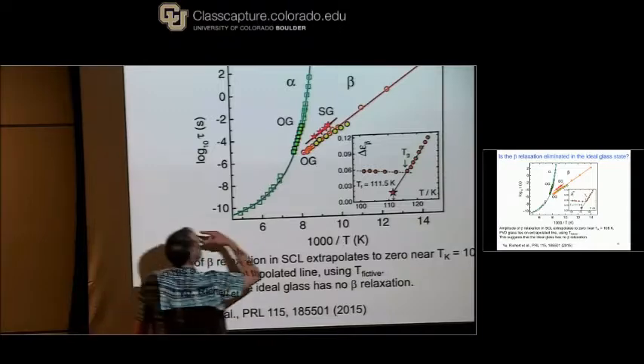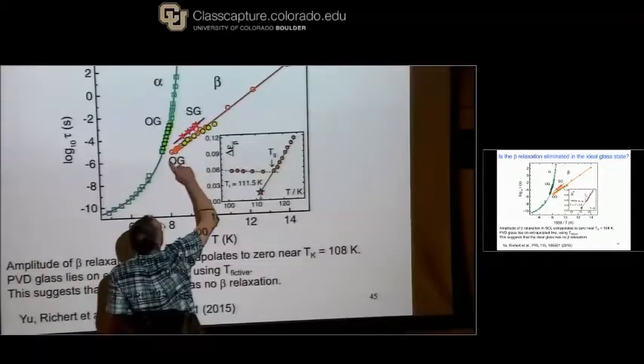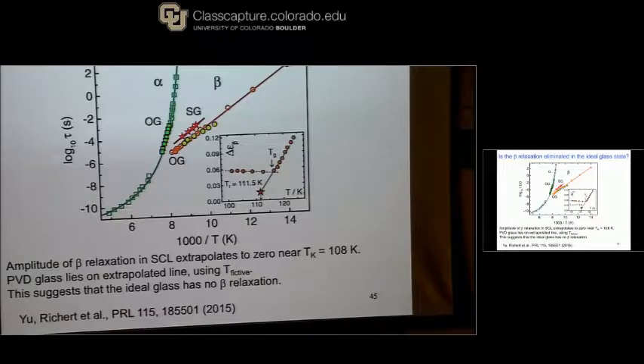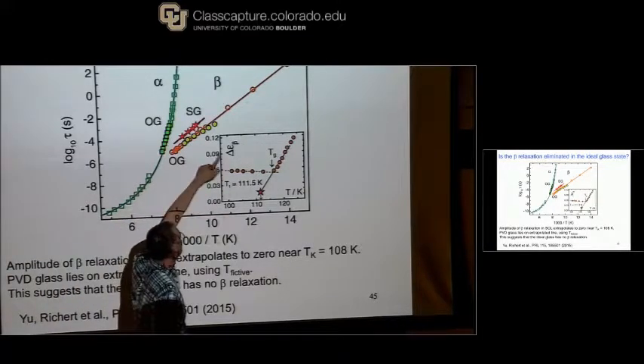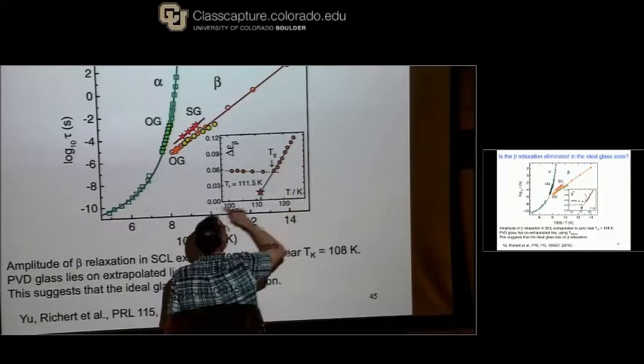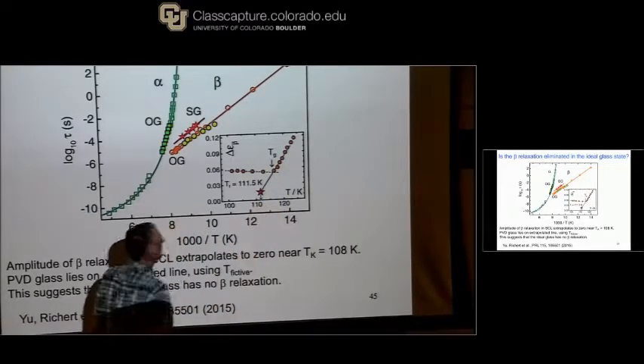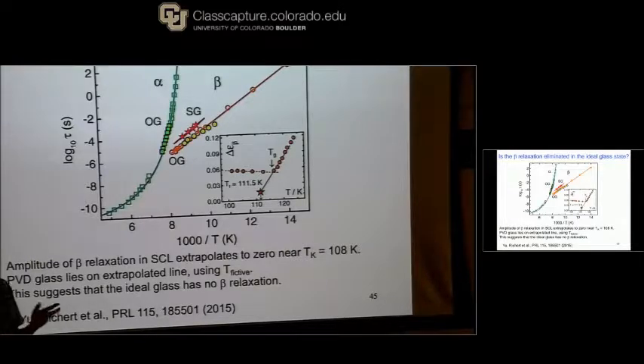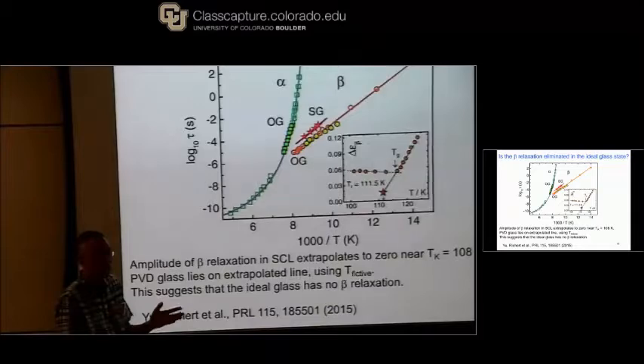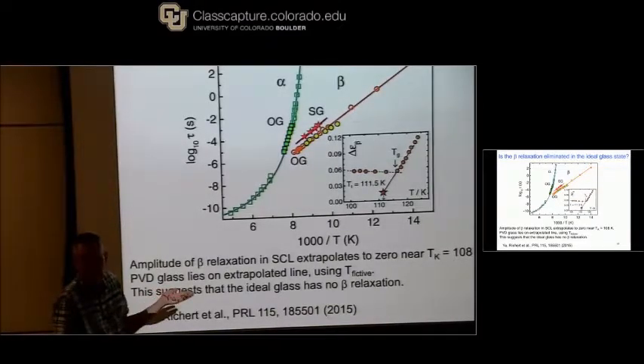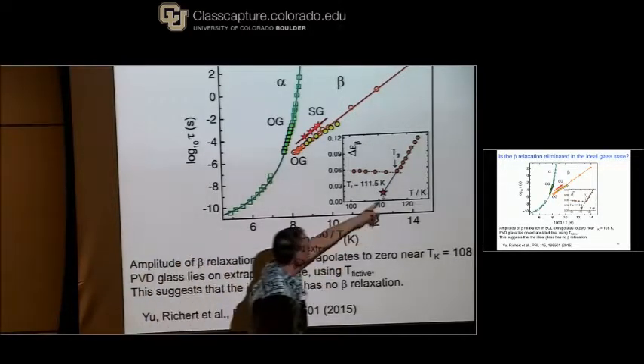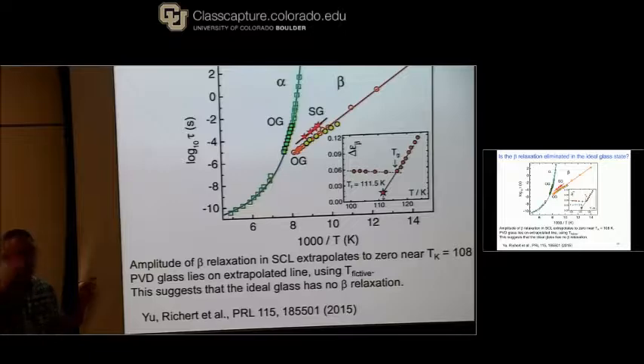Okay, so this is the relaxation map for our experiment. This is the alpha process. This is the beta process for the liquid-cooled glass. This is the beta process for the vapor deposited glass. But the most important plot is right here. It's the inset. This is the amplitude of the beta process in the equilibrium supercooled liquid as you go down in temperature. And if you take that and you just do a linear extrapolation, it hits 0 at about 109 Kelvin, and the Kauzmann temperature is 108 Kelvin. Okay? So if I just use equilibrium data and extrapolate, it looks like the beta process would go away when I made the ideal glass. And that star is our sample. And it looks like it's on that extrapolation.